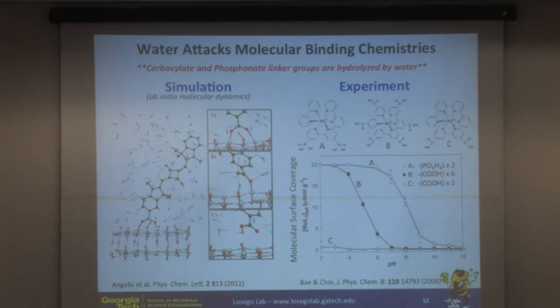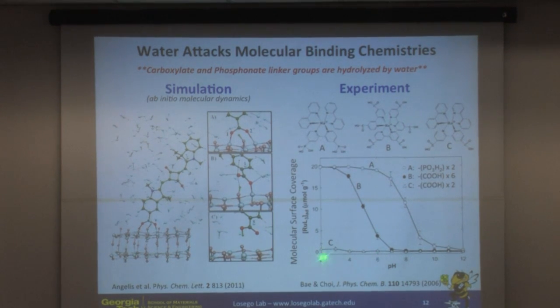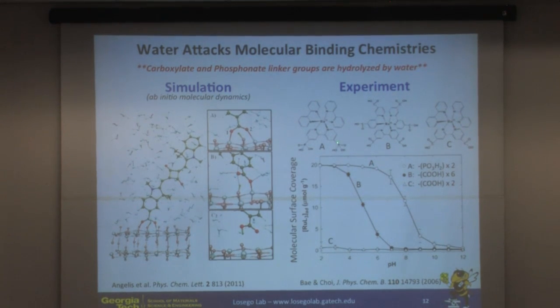Another issue that can happen is really a balance of charge. This is an experimental study where they're looking at the surface coverage of different dye molecules as a function of pH. Again, in an aqueous environment, changing the pH. As you change the pH, you're going to change the zeta potential of the surface, essentially the surface charge, right? In this case, we're looking at a TiO2 surface. When you go below about pH 6, you get a positive charge on the TiO2 surface. Above pH 6, you get a negative charge. These species are predominantly negatively charged, but as we go to lower pHs, we would expect that the positive charge on the surface would start to attract these molecules to the surface and create attachment.